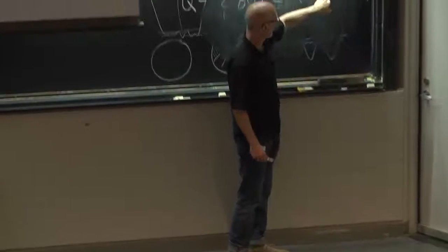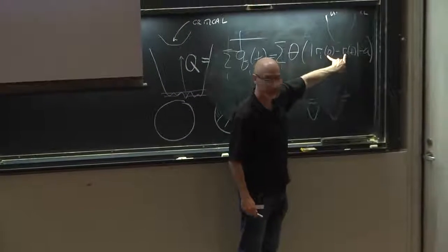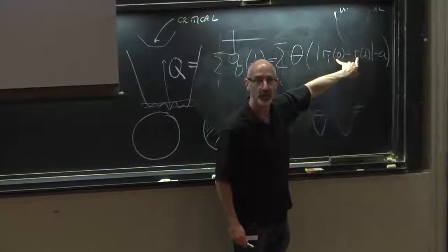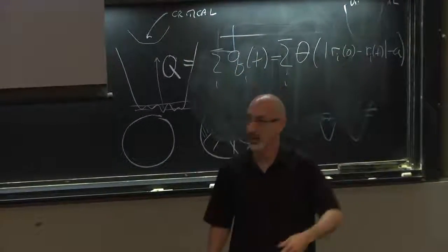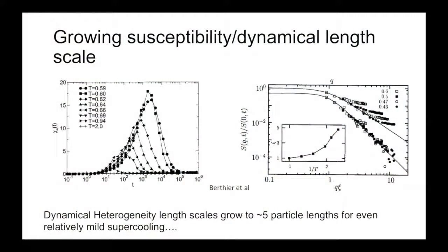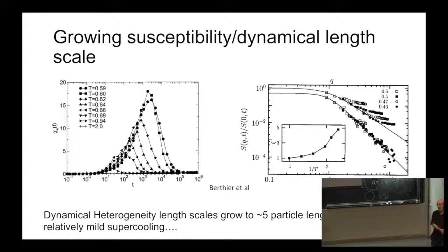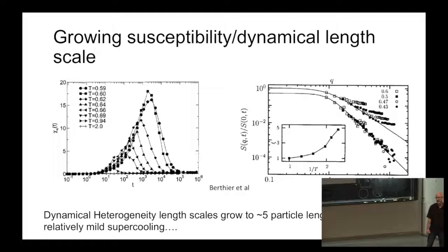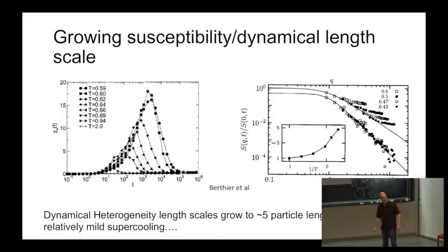So it is measured as the displacement in some time interval. And the result is going to depend on the time interval. As you see here, there's a peak in this, but if I let time get very, very large, everything is decorrelated. The whole system is relaxed, and it's as if it's not critical at all. So the criticality is really in the dynamics, and you have to look at the right length scale and time scale to see anything. The variance also shows up in space, right?